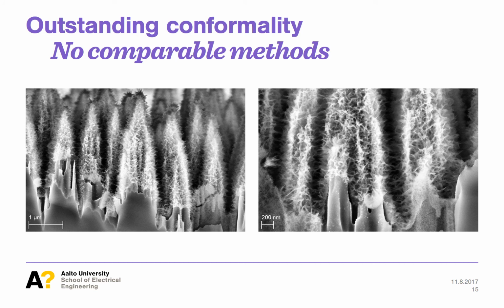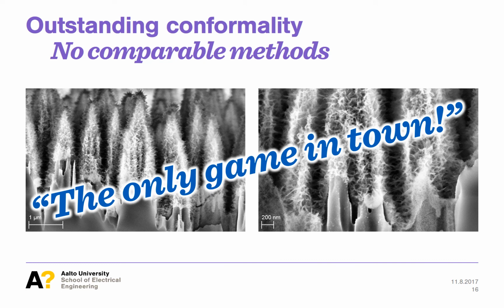As I have mentioned, atomic layer deposition enables conformal coating of substrates with extreme topography. Here, you see surface of black silicon coated with grass-like alumina. Not only has alumina deposition smoothly covered all the sharp peaks and the deepest trenches, but the transformation to nanoporous state also did not distort its conformality. It is vivid that grass-like alumina anti-reflective coating inherits outstanding conformality from atomic layer deposition. No other anti-reflective fabrication methods have comparable ability. So basically, it's the only game in town.